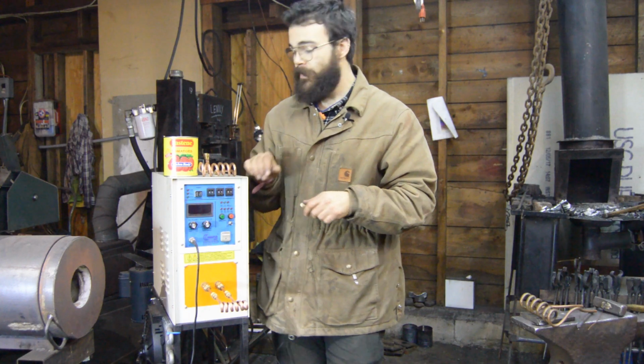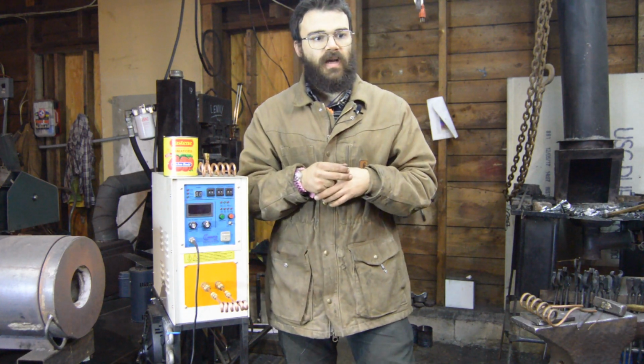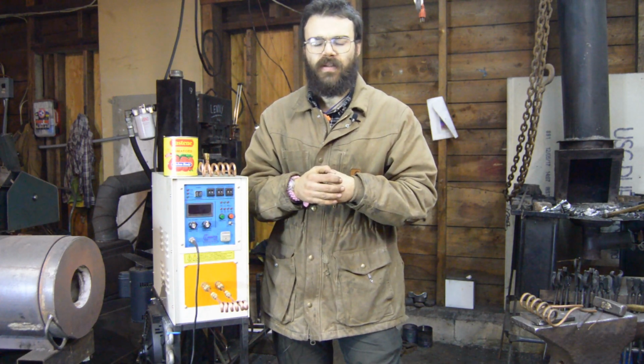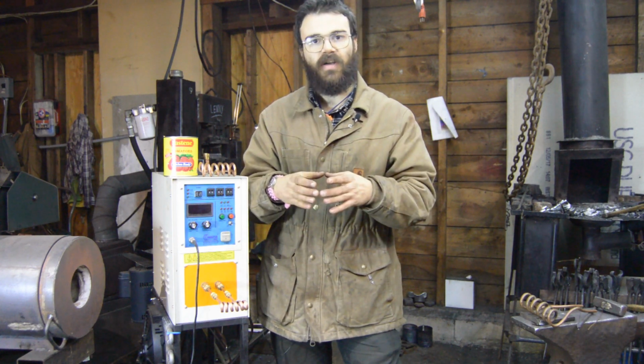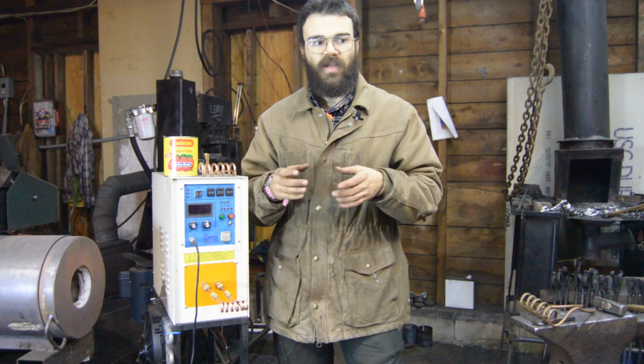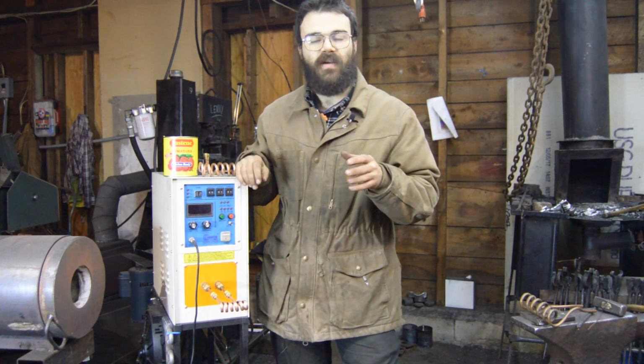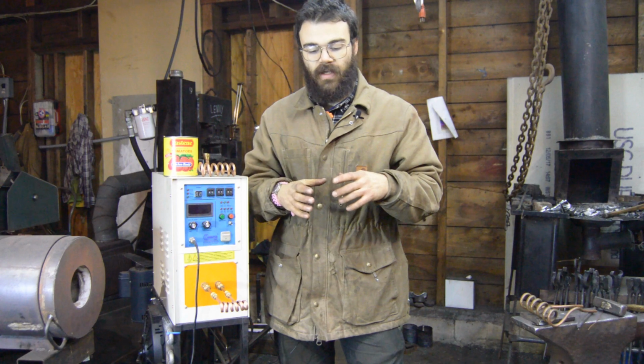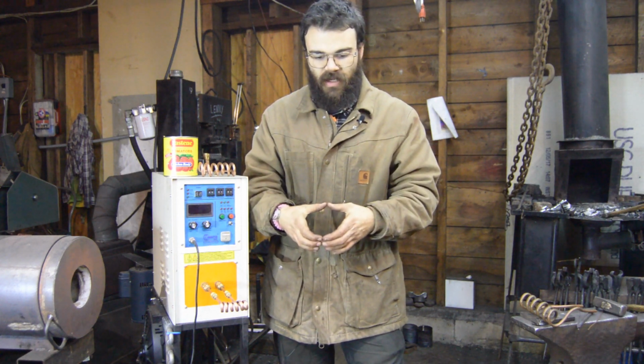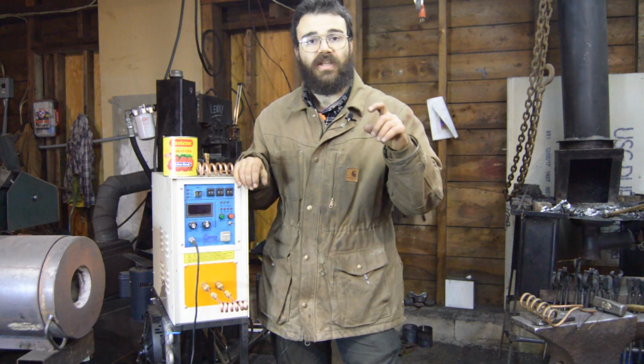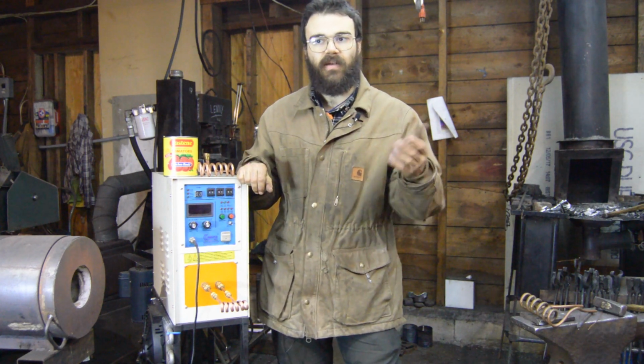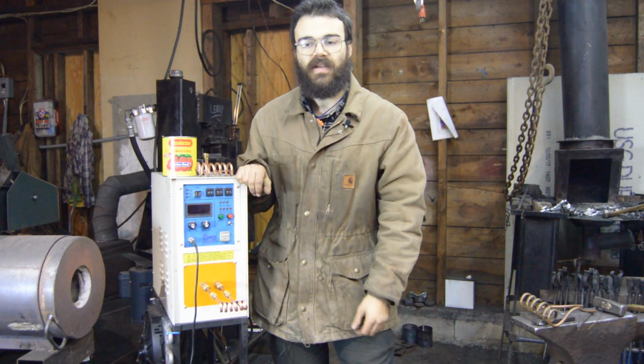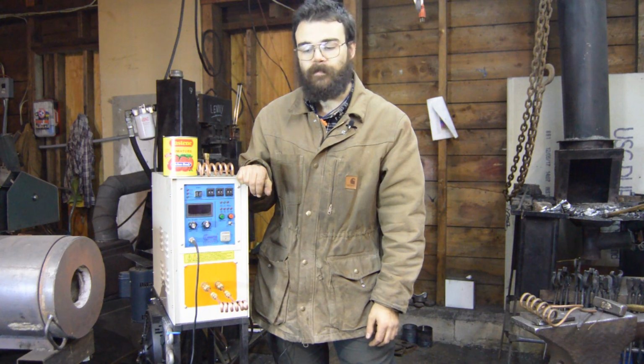For single-turn coils, and this only really applies if you're doing something like I spoke about before with a solid block of copper in a loop with a cooling tube on the outside, you want to keep those within about 1/2 of the ID. So if you have a 3-inch single-turn coil, you want to keep it less than 1.5 inches tall, and that just has to do, again, with the passage of the magnetic flux. Any more than that, you're just turning it into a big heater.